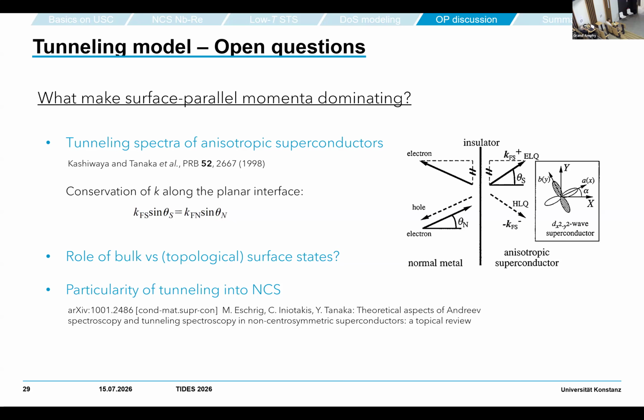Not in detail, but I just wanted to allude to the fact that it's different in these two directions, and I think this is a signature that we have some intrinsic anisotropy. It was the very same position, the same spectrum, and without magnetic field it went back to the same state, so it was a stable thing. Still, the development in the magnetic field was different, so for me it's just a signature that there is something anisotropic going on. I didn't want to say more than that.